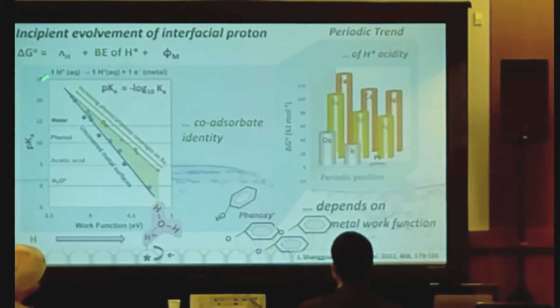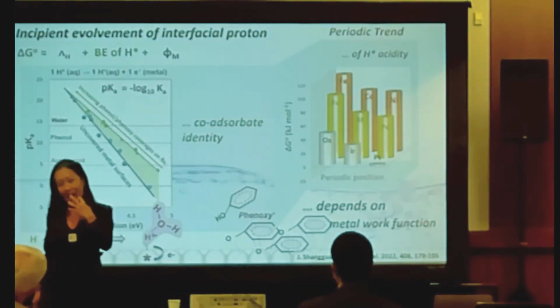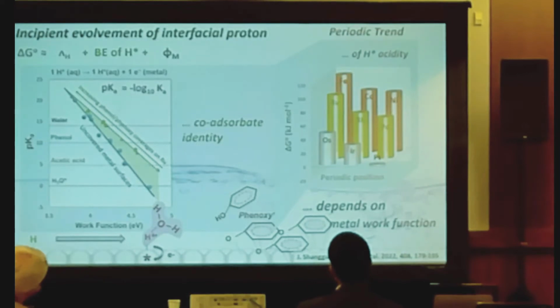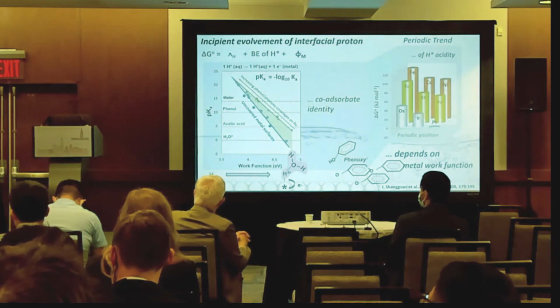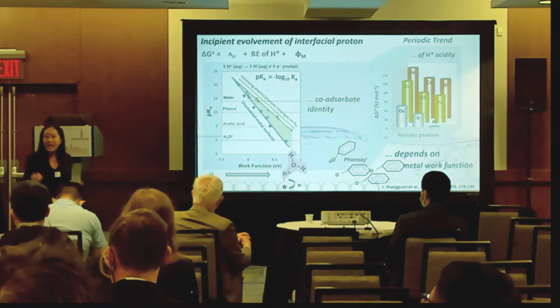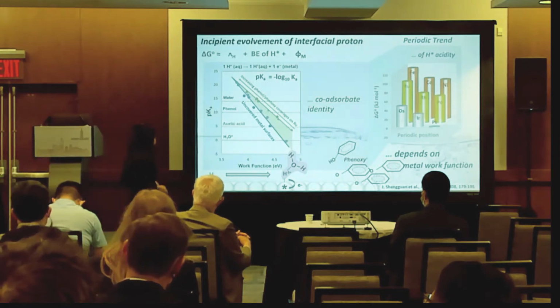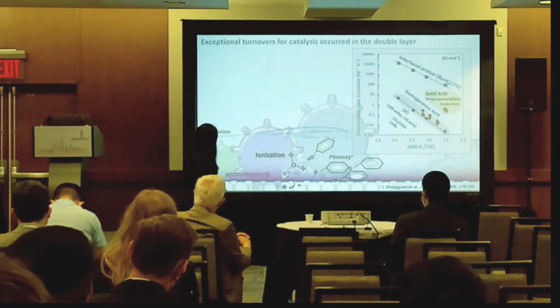The other point we want to mention is that the pKa of this value indicates that hydrogen is a weak acid. If we dissociate it on a transition metal surface, we have a hydrogen atom, we can also have hydronium ion, and we actually need both. You cannot always have only proton attack to complete a chemical reaction. You must have hydrogen atom balanced with the hydronium ion, and these two chemistries acting together enable a complete turnover. So what we visualize here is the following.